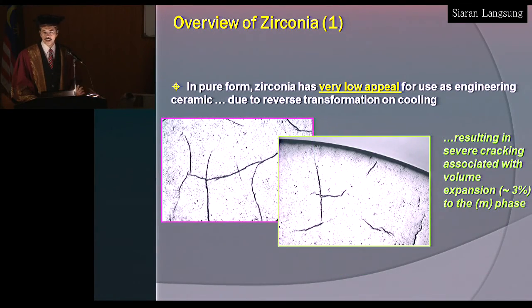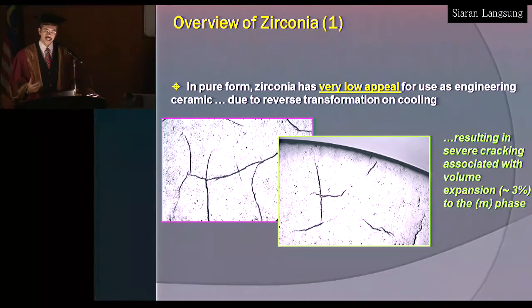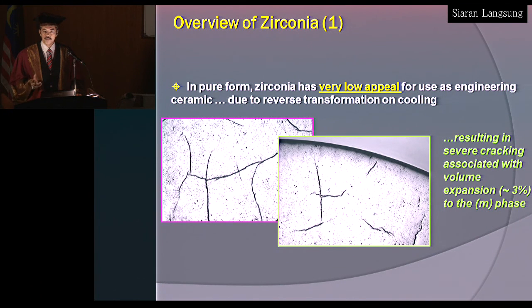So what's the problem with that? On heating, there is a volume shrinkage. On cooling, there is a volume expansion. Now, this in turn creates stress in the structure. As I showed earlier, the dimensions are different, the angles are different. And therefore, pure zirconia has very low appeal as an engineering ceramic due to the reverse transformation. And normally, the sintered body exhibits severe cracking because of the volume expansion.